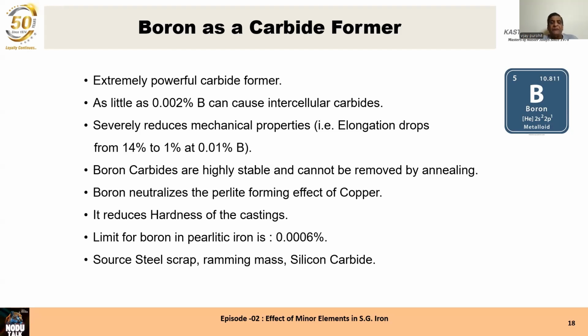Boron neutralizes the pearlite-forming effect of copper. If boron is present in your pearlitic iron, it will not give you the hardness. It reduces the hardness of pearlitic cast irons, SGIN. The limit of boron in pearlitic iron is 6 ppm, 0.0006%. 6 ppm is the limit for boron in pearlitic irons. It does not have that much bad effect on ferritic irons, but it is extremely bad if it is present in pearlitic irons. The sources of boron are steel scrap, ramming mass, and silicon carbide that people use. It's a good material to be used, but make sure the boron is less than 6 ppm in pearlitic irons.